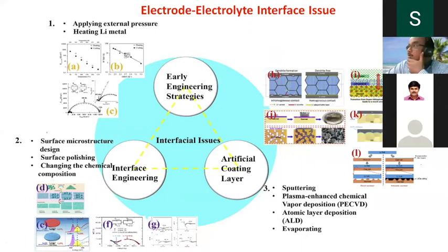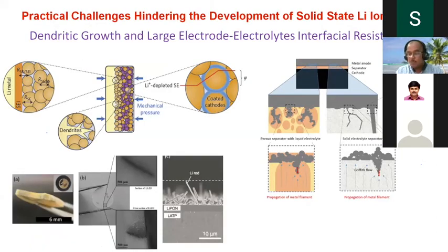This is how we spent the last 10 years overcoming these electrolyte interface problems. In the initial early engineering stages, we applied external pressure and heated the lithium metal. Later we started with interface engineering: surface microstructure design, surface polishing, changing the chemical compositions. Then we entered artificial coating layers between the electrode and electrolyte. We used sputtering, plasma, chemical vapor deposition, and ALD techniques. So many techniques, because several people started to do research on this, and slowly, one by one, we were able to resolve these issues.